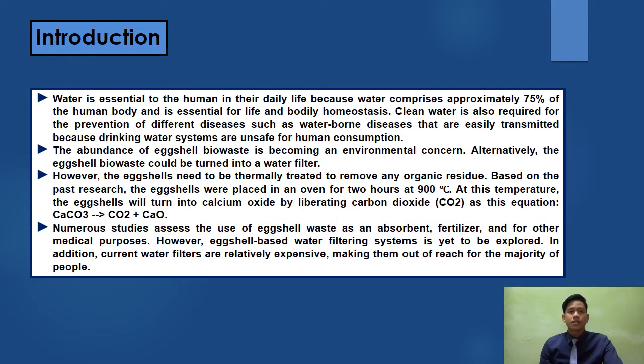However, the eggshells need to be thermally treated to remove any organic residue. Based on the past research, the eggshells were placed in an oven for 2 hours at 900 degrees Celsius. At this temperature, the eggshells will turn into calcium oxide by liberating carbon dioxide. Numerous studies assess the use of eggshell waste as an absorbent, fertilizer, and for other medical purposes. However, eggshell-based water filtering systems is yet to be explored. In addition, current water filters are relatively expensive, making them out of reach for the majority of people.